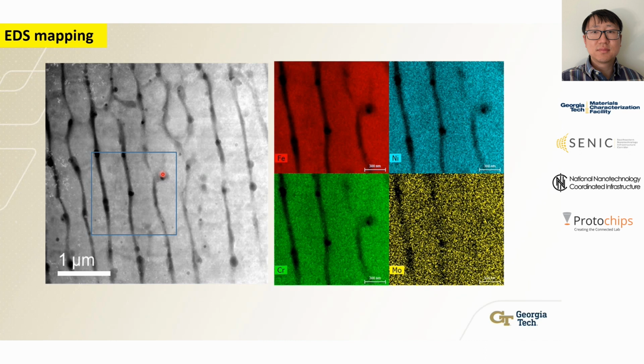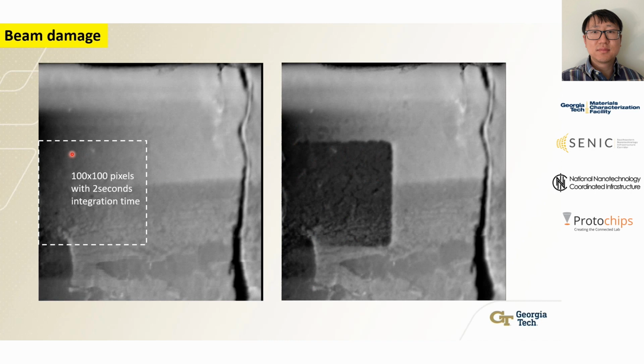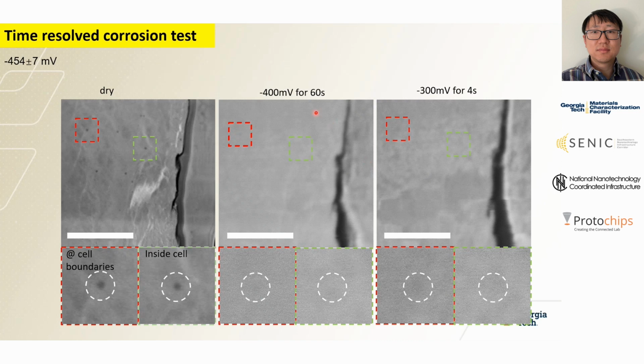But before we do that, we notice that if we apply the electron beam with a long integration time, like shown here, after we take the EDS map with 100 by 100 pixels and 2 seconds integration time per pixel, then the electron beam damages the sample under the potential. To minimize the beam damage effect, we maximize the flow rate of the solution, and we also flush the corroded material with DI water for at least 10 minutes at the maximum flow rate. After doing that, we can see the beam damage is minimized.